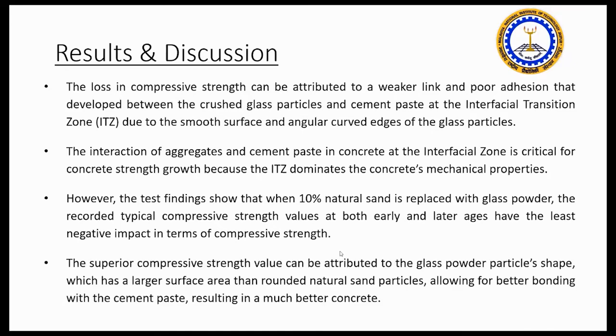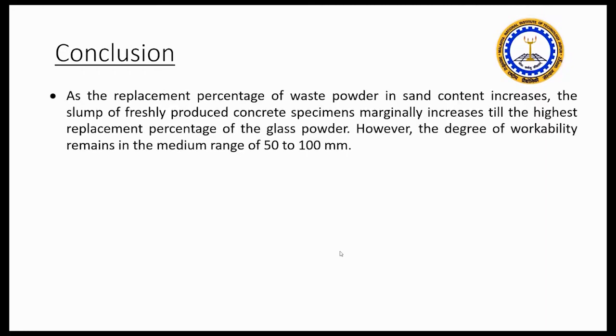The superior compressive strength value can be attributed to the glass powder's particle shape, which has a larger surface area than rounded natural sand particles, allowing for better bonding with the cement paste, resulting in much better concrete.